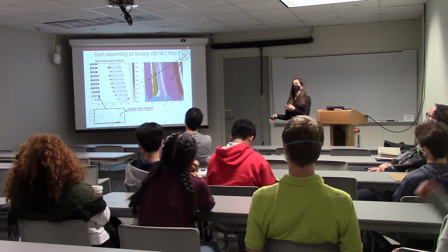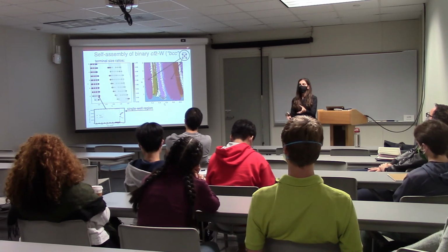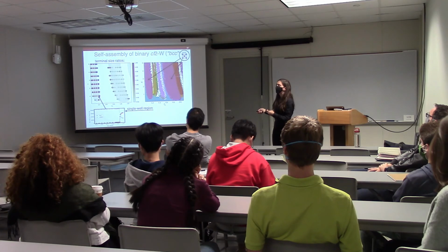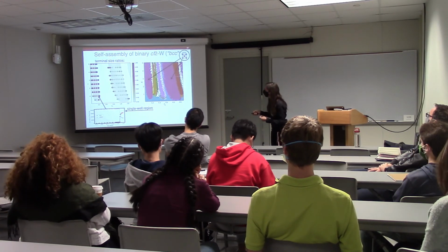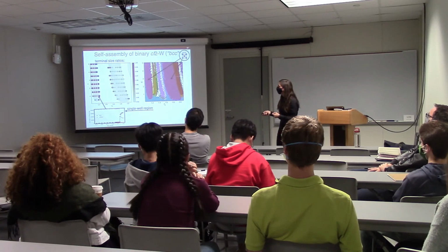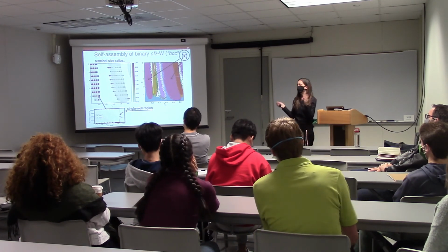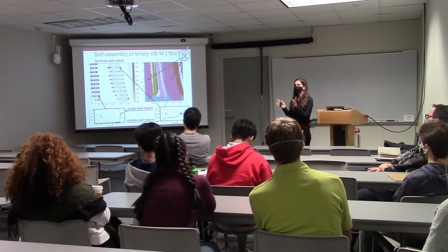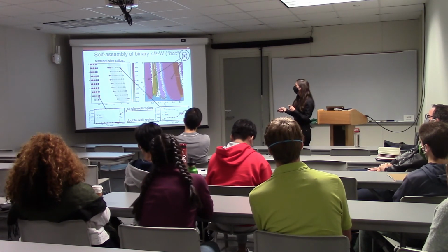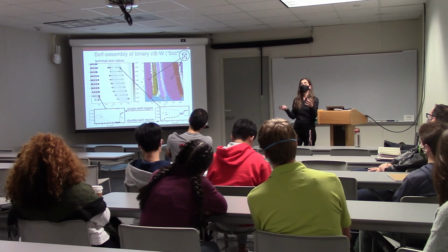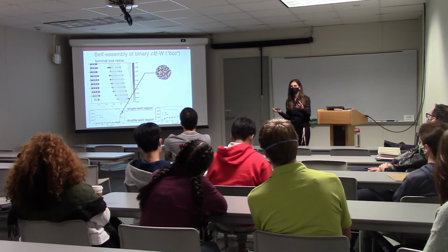The other aspect of this is not just that the double well region is better, but also the breakdown behavior is a little different. In the single well region over here, what essentially happens is you have a lot of particles in the correct environment, which is supposed to be orange. And then at some point when you change your size ratio, you make your sizes slightly too different, it breaks down and never comes back, and the particles are just disordered. In the double well region, you have more fun stuff happening. So it goes down a bit, and actually the size ratio that's displayed here is the most conservative estimate, the first step down. So you can see, even as this happens, even at about 90%, you still have a sizable chunk of particles in the correct environment, and that's because of what happens locally.